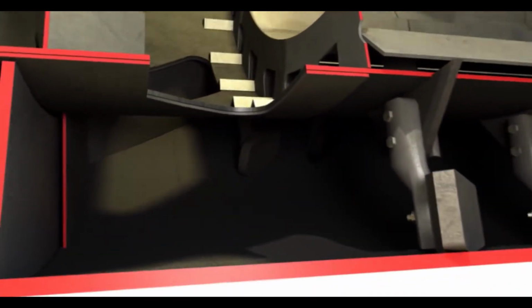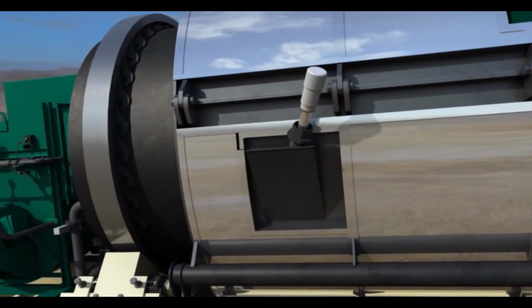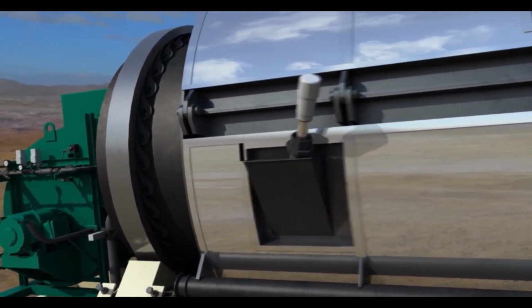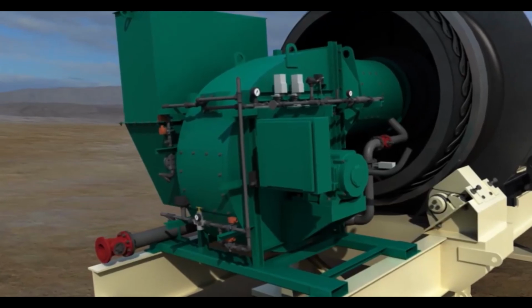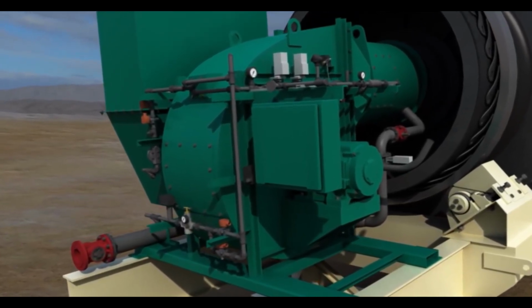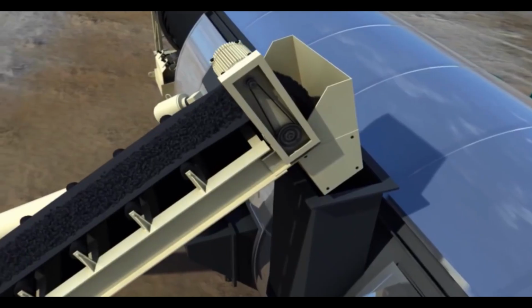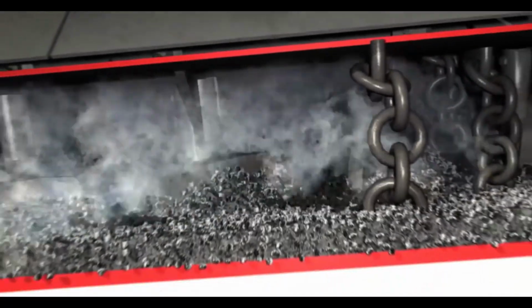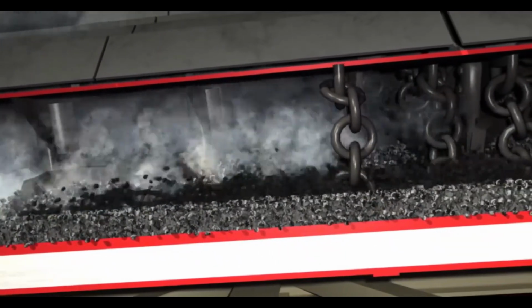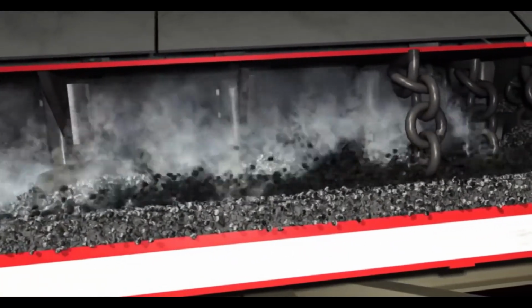Once heated and dried, the aggregate leaves the drying chamber and enters the insulated mixing chamber. At this point, an infrared sensor measures the temperature of the hot aggregate and sends data to the burner control for automatic adjustment of the burner output. The target temperature for the virgin aggregate will be adjusted relative to the volume of RAP that will be introduced to the outer drum. The hot aggregate transfers heat to the RAP in the outer chamber, driving off moisture as steam. This minimizes emissions because the RAP does not contact the hot gas stream in the dryer chamber.